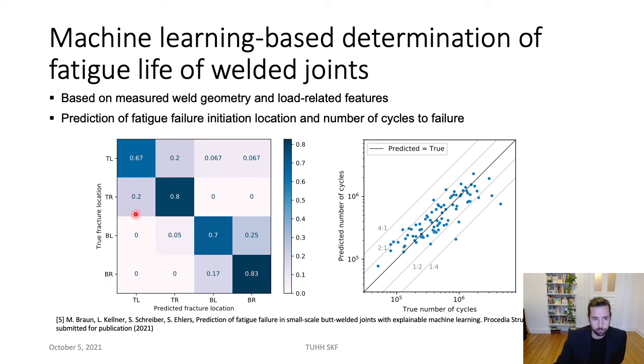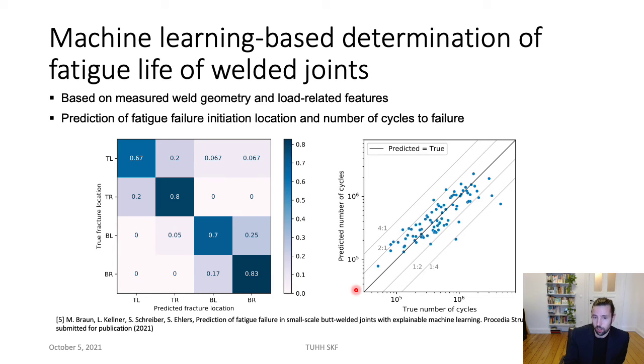What we see is that the algorithm is quite good at assessing whether failure initiated on the top side and similarly on the bottom side. It is also quite good at predicting the actual failure location in certain categories — the diagonal values represent cases where the predicted failure location matched the actual one. We then used an explainable machine learning algorithm with both measured geometric input parameters and load-related factors to predict fatigue life, and again the algorithms are quite good: the majority of tests fall within a factor of two of the actual fatigue life.